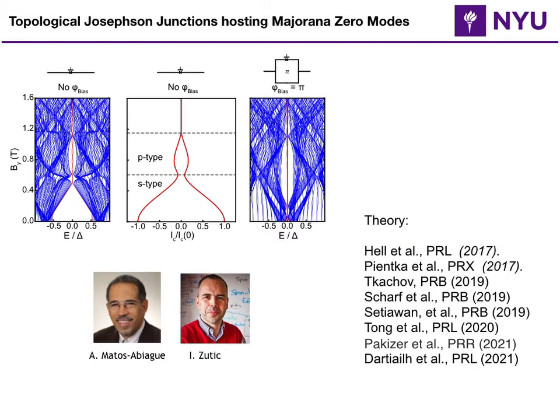And we look at this physics that has been predicted from 2017 of how to realize Majorana fermions. The big idea there was that if you don't bias the junction and you look at the spectrum, the energy as a function of magnetic field, you are gapped at first. As you apply the magnetic field in the right direction, which is along the junction, you close the S-wave gap and reopen a P-wave gap, and that new gap, the topological gap, hosts Majorana fermions, which shows up as a zero energy mode.